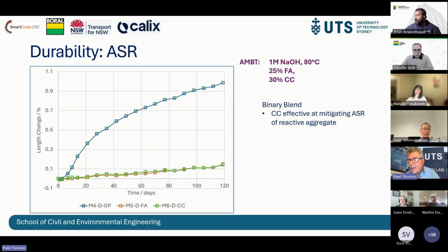This is part of that new standard AS 1141.60.3, using blended cements in mitigation of ASR. This particular calcined clay is slightly less good than the fly ash, so we needed 30% substitution rather than 25% for the fly ash. But essentially, both fly ash and calcined clay are excellent in mitigating ASR.